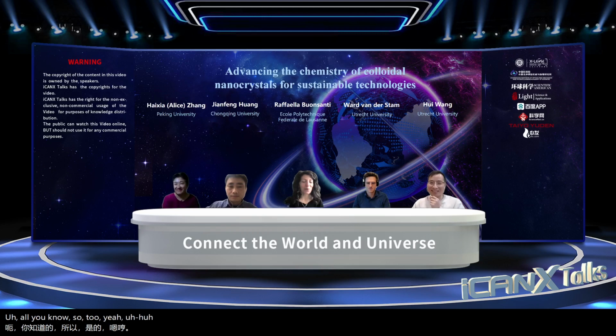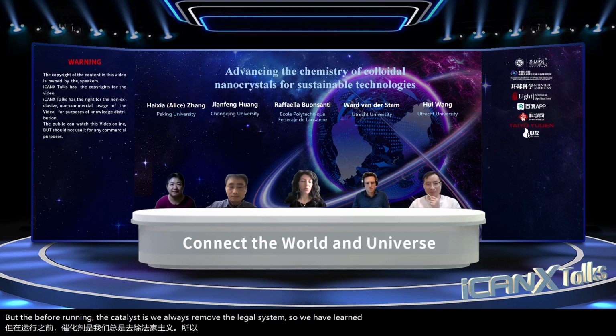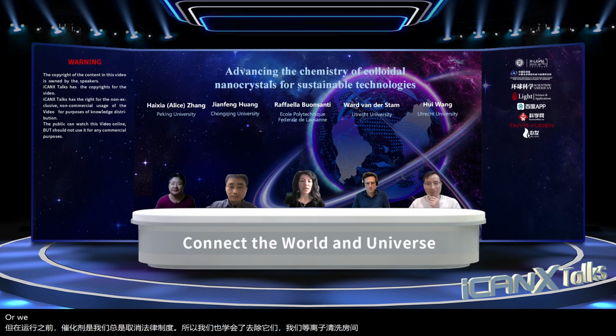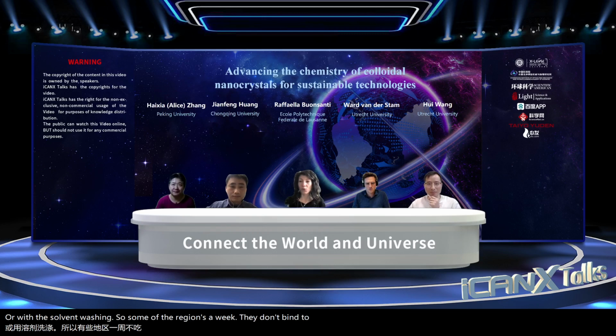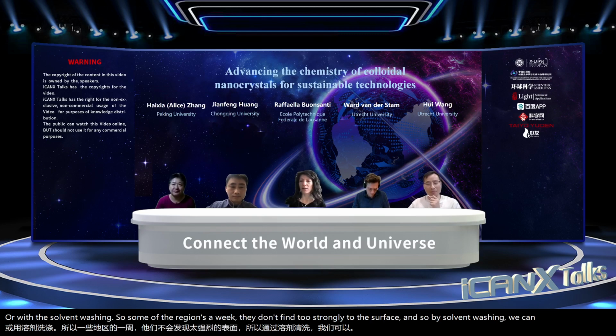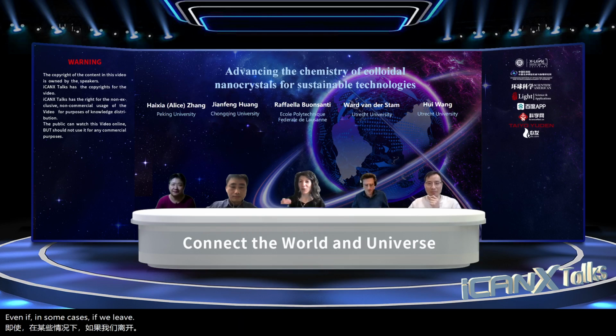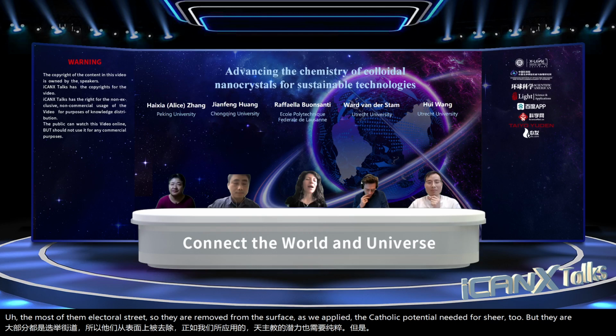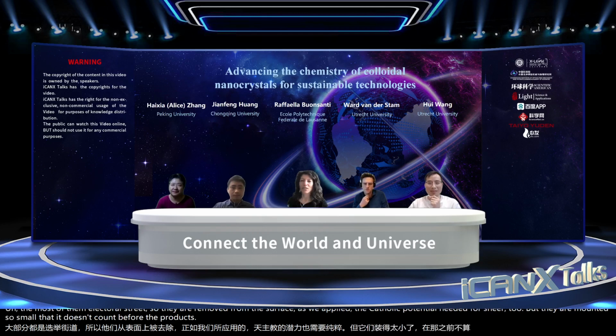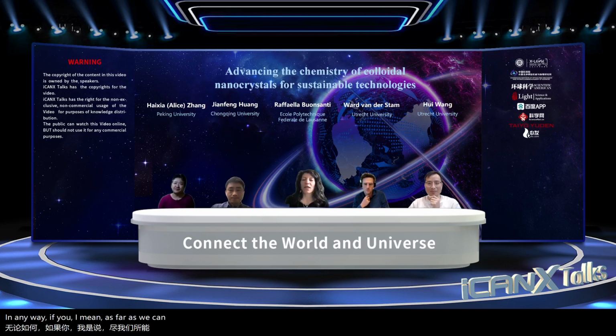It's a very good question, and indeed this is something that I don't show. I normally have additional slides, but before running the catalysis, we always remove the ligands. We have learned to remove them either with plasma cleaning or with solvent washing. Some of the ligands don't bind too strongly to the surface, so by solvent washing we can remove them. Even if in some cases we leave them on the surface, most of them electrostrip. So they are removed from the surface as we apply the cathodic potential needed for CO2 reduction, but their amount is so small that it doesn't count for the products that we generate. And anyway, as far as we can tell from GC measurements, the product distribution remains pretty much the same when we strip the ligands and when we don't. We don't see huge variation.